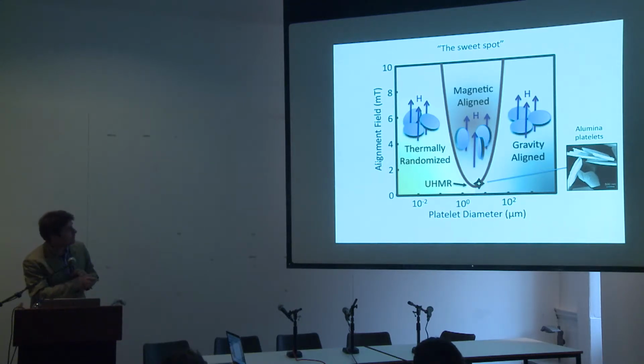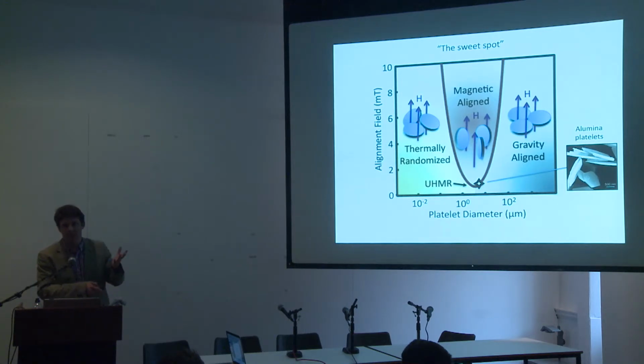Why is that? Here we look at the field required for alignment as a function of the size of your platelets. If you're very small, and that would be the range, for example, of carbon nanotubes that were mentioned this morning, then these particles are very Brownian. They're thermally very active, and therefore you need very high fields for alignment. If they're very big, and now you think about aggregates and very large particles, again you need very high fields because gravity plays a dominant role there. But there's a sweet spot in between, for particles between, say, 1 and 50 microns, where it's extremely easy to align them.